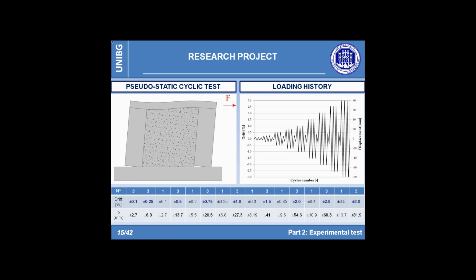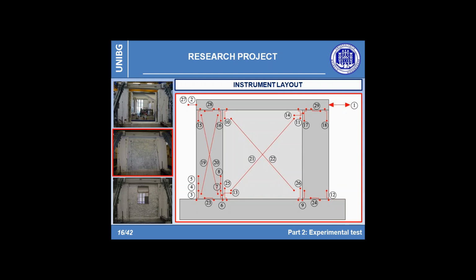From this step forward, the amplitude of the cycles is incremented each time by a value equal to 0.5% up to the collapse of the structure. In particular, for each drift level, 3 complete cycles have been repeated. As briefly outlined, the adopted protocol has been performed by monitoring the displacement in terms of interstory drift. The horizontal displacement has been registered at the top, in the middle of the upper beam, by the instrument named 2 and 27, while the height of the structure has been assumed as the distance between the point of the applied load, labeled 1 in the picture, and the base of the structural walls, in this case equal to 2.73 meters.